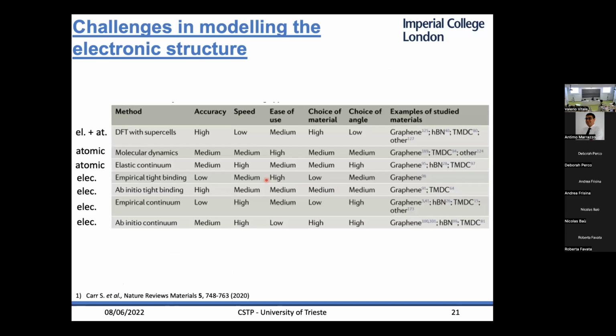Right. So there are different ways people have tried to tackle this issue of understanding the electronic structure and the atomic structure of these systems, and there are different levels of accuracy. Of course, one would like to do everything at the DFT level, density functional theory. The accuracy of DFT in terms of the band structure and the atomic structure is quite high, but the speed is low, and you can't really have all the angles that you want, because at some point you hit the N cubed scaling of density functional theory, so you can't really go to very large systems.